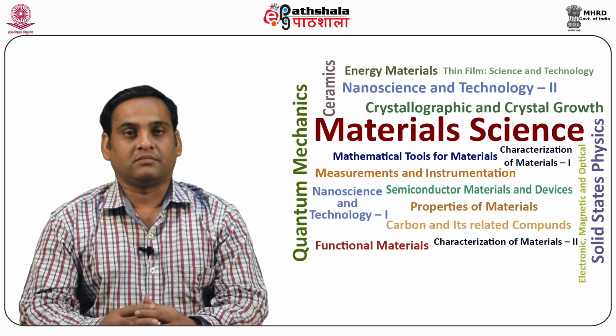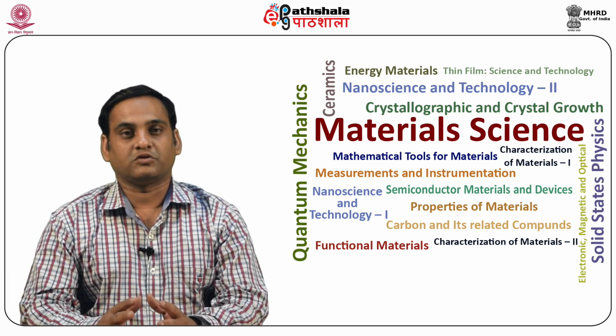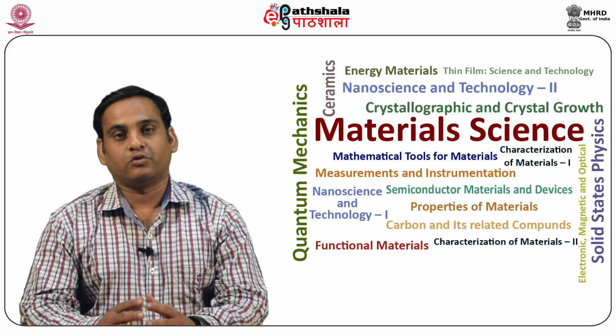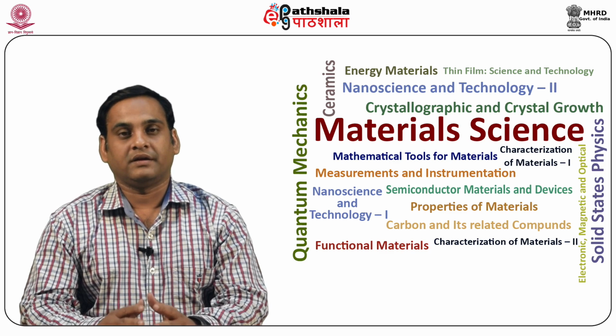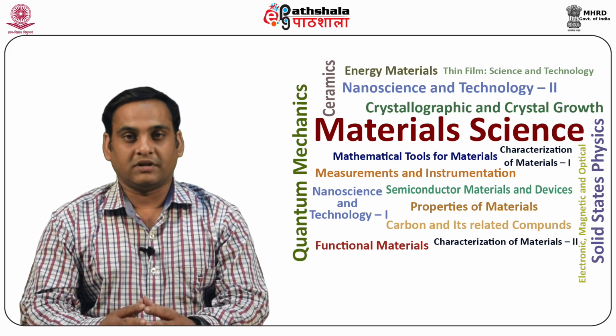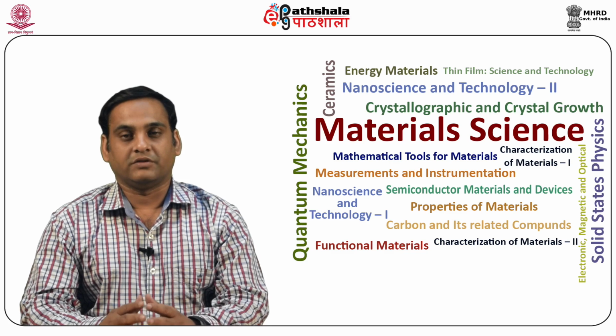Molecular relaxation time. Molecular relaxation time may be expressed in terms of the viscosity of the liquid and the temperature as tau equals 4 pi eta a cube by kT, where a is the molecular radius. The molecular relaxation time is assumed to be due to the inner friction of the medium that hinders the rotation of polar molecules. However, tau m is a function of viscosity.